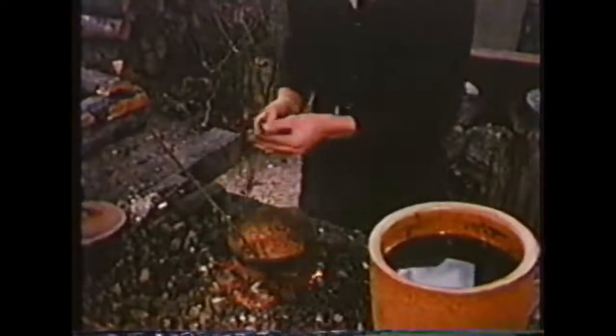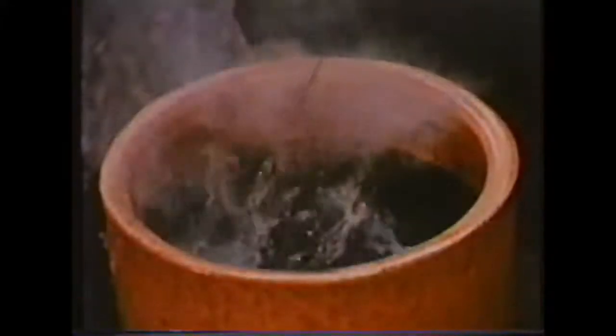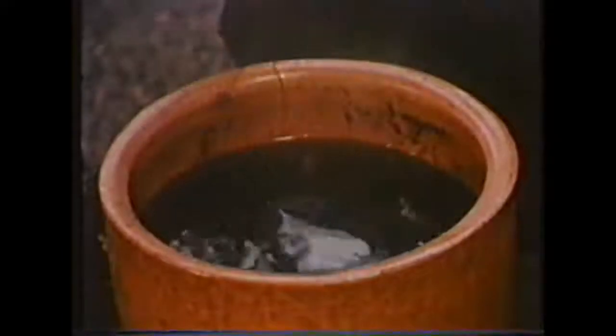Springs are tempered in lead heated to the boiling point. By submerging the springs in the molten lead, you get an even heat throughout the thick and thin parts. After heating, they are quenched in linseed oil. After quenching, the springs are very brittle. They are then polished, put on a bar in the forge, and heated. This softens them somewhat and gives the springs flexibility.